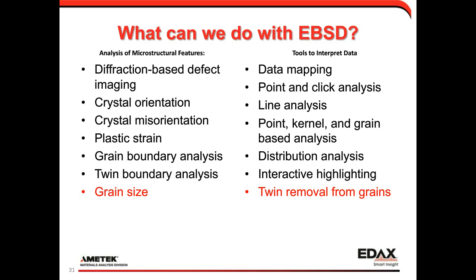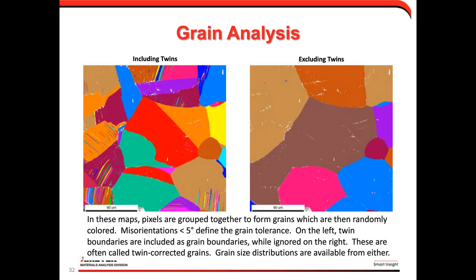The next thing we can do is we can talk about grain size measurements. We can combine that with the idea of measuring grain sizes with and without twins and twin removal from grains. So to measure the grain size, what we need to do is we need to group together pixels of the same orientation. So to calculate grains, we need to group together points that have the same orientation. But to do that, we have to define some sort of a grain tolerance angle to decide when one grain changes from one to another. So in this case, I've used 5 degrees as our grain tolerance angle.